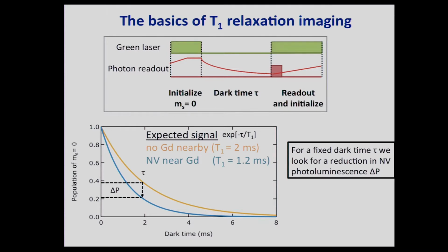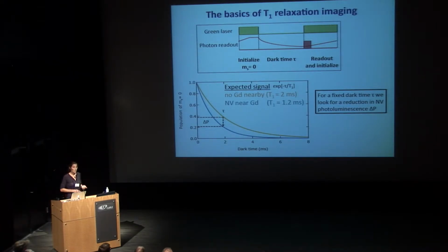Okay. In the presence of gadolinium, though, if we were to zoom in on this part of the experiment down here, without any gadolinium we might get a characteristic relaxation curve that looks like this. With gadolinium, that will enhance the relaxation of the NV center, causing it to relax more quickly, and we get the blue curve. And so if we fix our measurement time to, say, in this case, 2 milliseconds, and look at the fluorescence of the NV center after letting the NV evolve during this dark time, we should see a change in the fluorescence signal. Okay. So that's what we're looking for. We're looking for a change in the fluorescence of the NV center when a gadolinium is brought nearby.